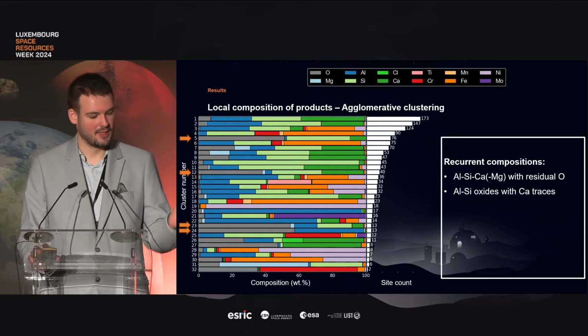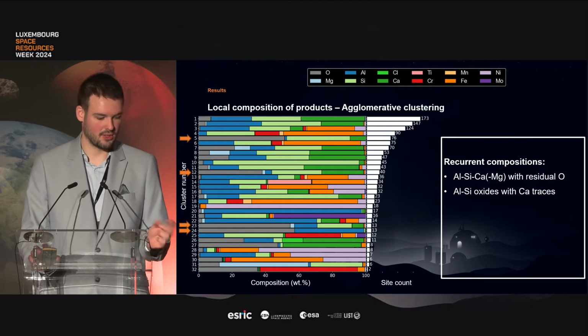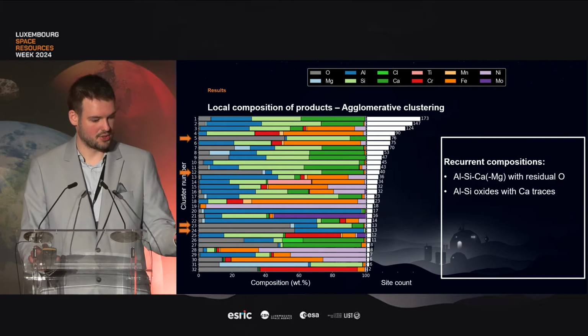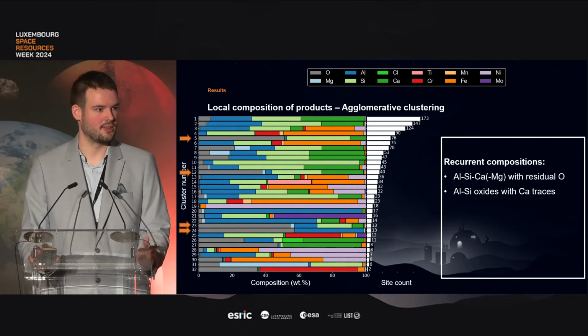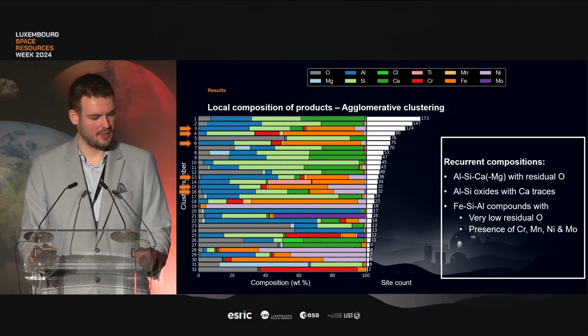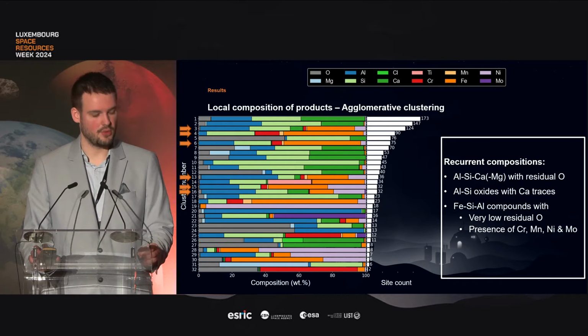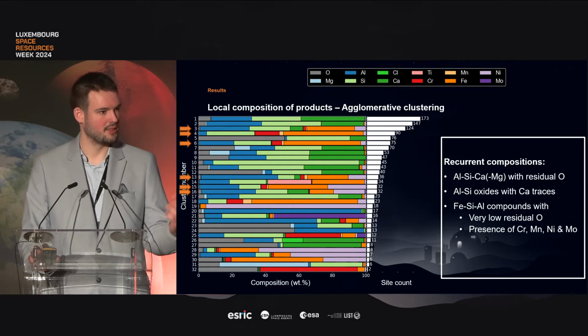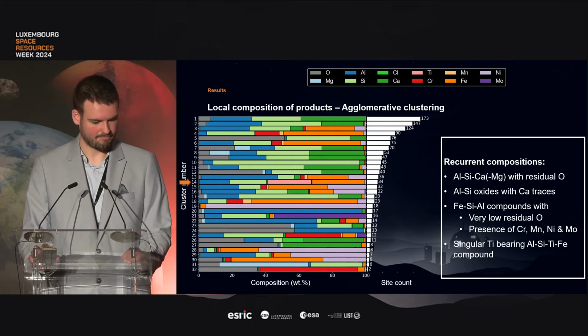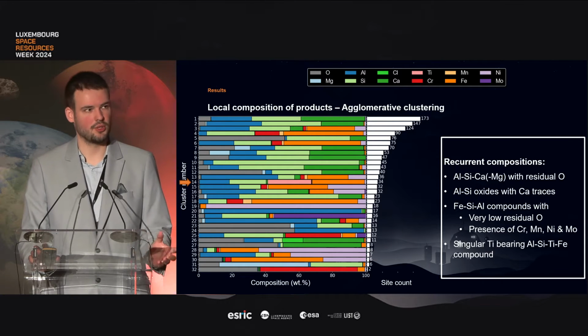Then we also have some more isolated aluminium silicon oxides that contain only residual traces of calcium. So the oxygen here is in gray, so those are very high oxygen-bearing compounds. And then the iron compounds, as I say, don't contain a lot of calcium, but iron will combine with the silicon and the aluminium. They have very low residual oxygen, and then the presence of those stainless steel-derived elements. And finally, titanium is also quite interesting, it always falls in the same quite narrow band of composition, which is aluminium, silicon, titanium, iron. So this is a very specific recurring composition.